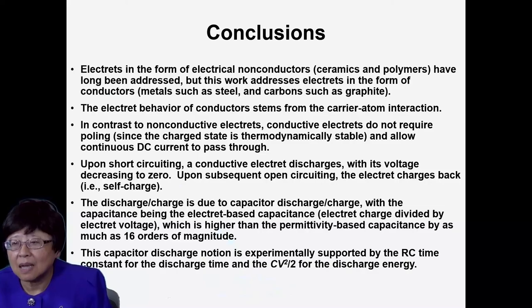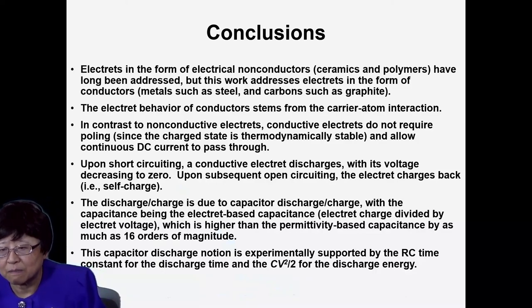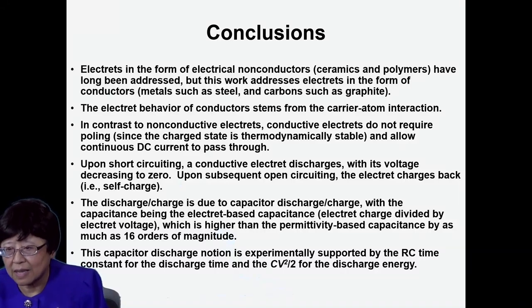Upon short-circuiting, a conductive electret discharges, with its voltage decreasing to zero. Upon subsequent open circuiting, the electret charges back, that is, self-charges. The discharge or charge is due to capacitor discharge and charge, with the capacitance being the electret-based capacitance, which is the electret charge divided by the electret voltage. And this electret-based capacitance is higher than the permittivity-based capacitance by as much as 16 orders of magnitude. And this capacitor discharge notion is experimentally supported by the RC time constant for the discharge time and the half CV squared for the discharge energy.